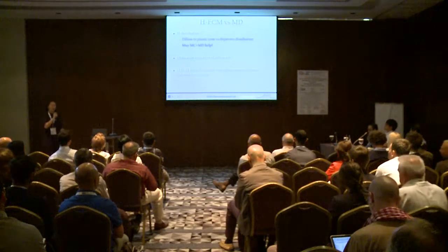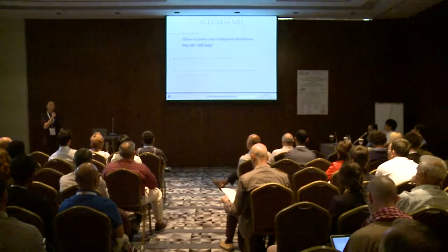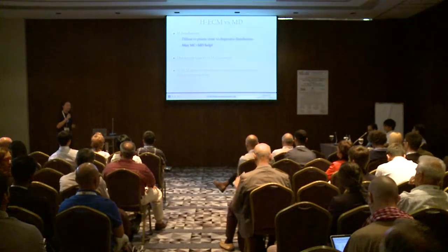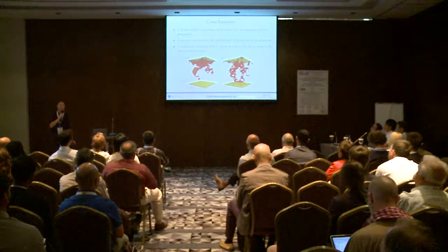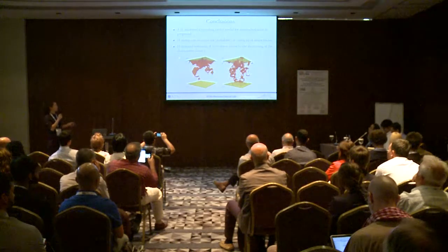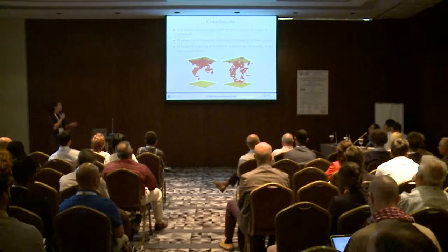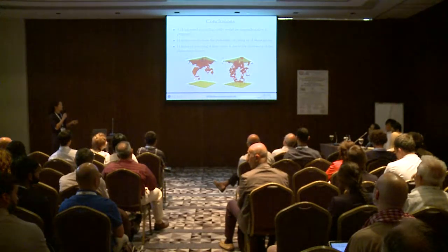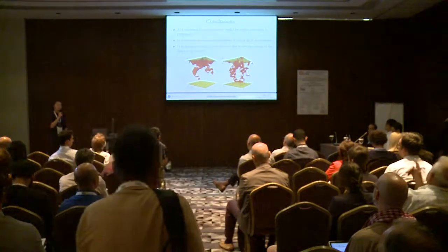The continuum model doesn't really contain a term to represent the dislocation avalanche, so we cannot predict the sudden drops during dislocation emission and movement in the continuum model. My conclusion is that this continuum model is a really crude model. We need a lot of refinement, but it's still possible to predict the indentation behavior. Hydrogen atoms decrease the probability of dislocation pile-up, so the softening of the flow stress is mainly due to the reduction of the dislocation density.